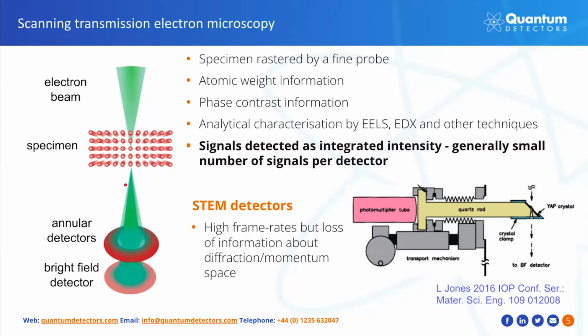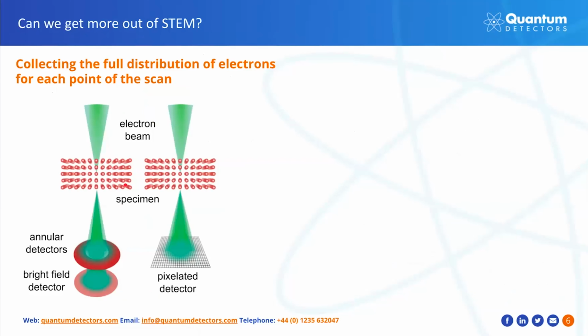The signals can be very wide-ranging. One of the most used techniques in STEM is the detection of electrons scattered elastically to large angles. This is used to recover atomic weight information from the sample. This information is usually captured with an annulus-shaped detector with a hole in the center to let the central, more intense part of the beam through. If we capture the center of the signal, we can collect bright field information with large phase contrast contributions. The conventional STEM detectors are generally fast, reaching close to megahertz frequencies. However, these detectors reduce the information-rich signals to a small number of intensities, and the distribution of the electrons is lost in the process.